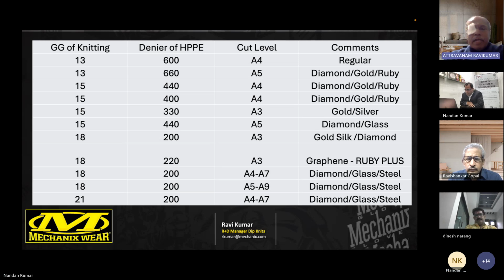Here what I have tried to explain is, depending upon the gauge of the knitting machine, right from 13 to 21, if you use a denier of the HPPE as mentioned in the table, what is the cut level against the ANSI standard that you can get? And what is the combination of material that you need to use? If I take the fifth line, that is 15 gauge, 330 denier, you get an A3 with a gold silk or a silver silk yarn. So for A3 of say 1200 to 1500 gram cut resistance, you don't have to use glass or steel. Just use a 330 denier, knit a 15 gauge liner, and you get an A3 cut level.